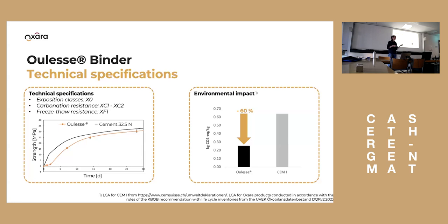or to carbonation. Quickly, carbonation: a cementitious concrete has a very high pH, so it's alkaline, and that high pH protects the reinforcement bars in the concrete. So for cementitious concrete, you have a protection from corrosion by the high pH of the concrete. And carbonation means that if the CO2 from the air ingresses the concrete, the CO2 reacts, and that reaction decreases the pH. So you want to make sure that the pH of your concrete stays at a high level so that your reinforcement bars are protected from corrosion.